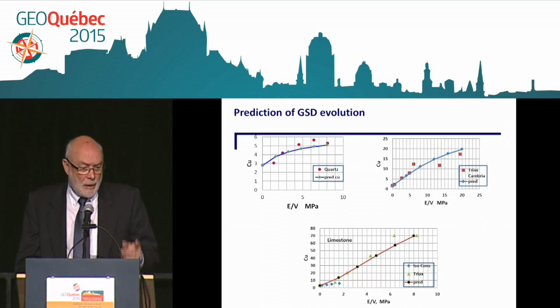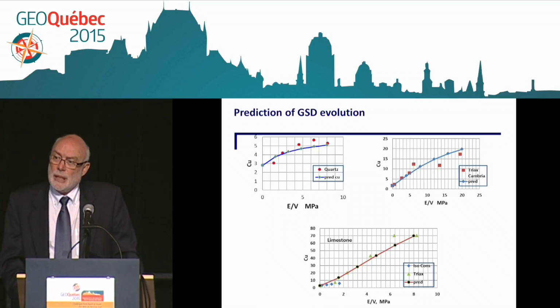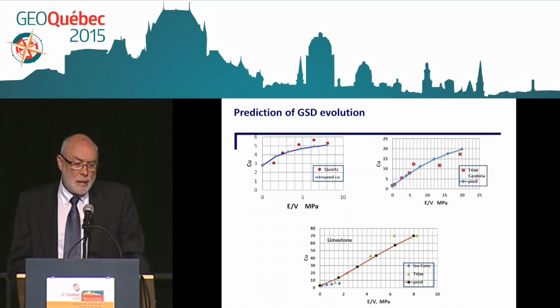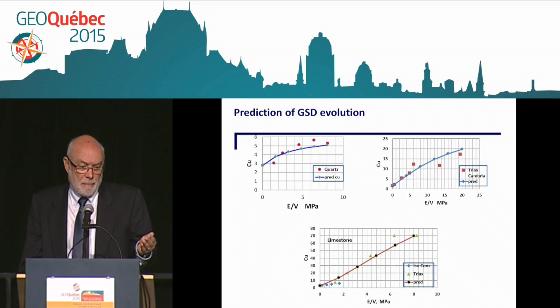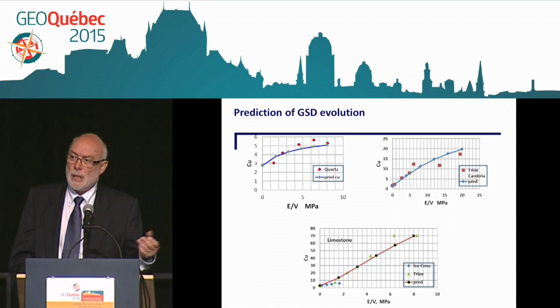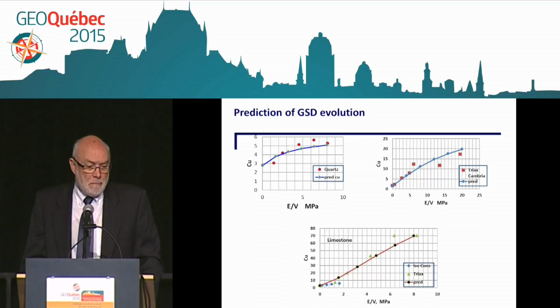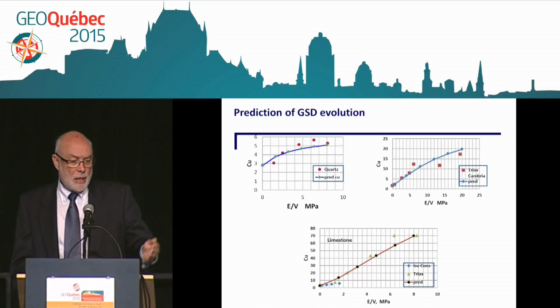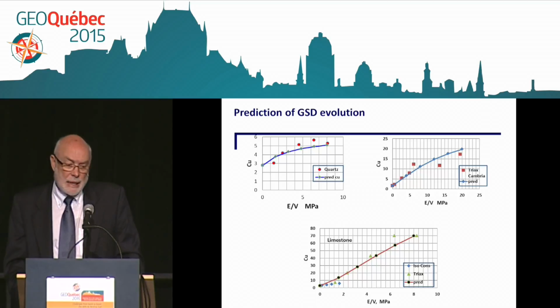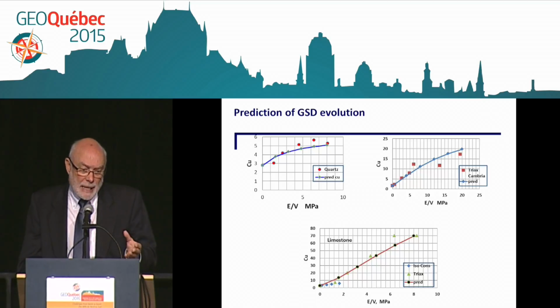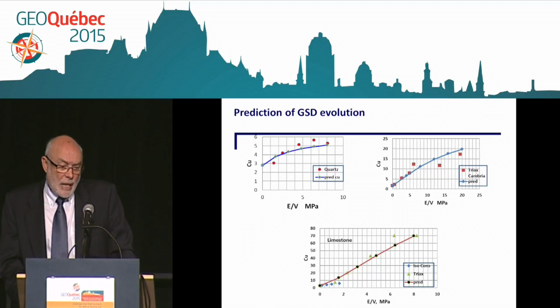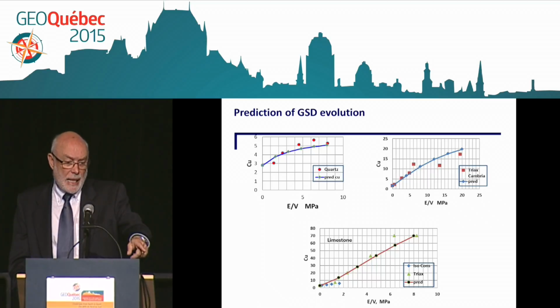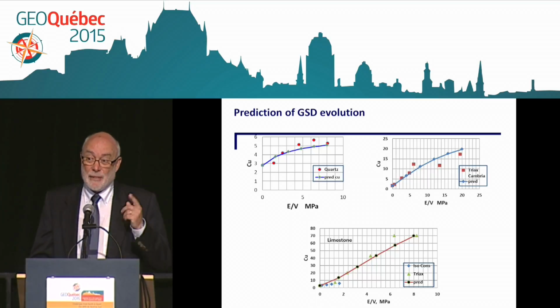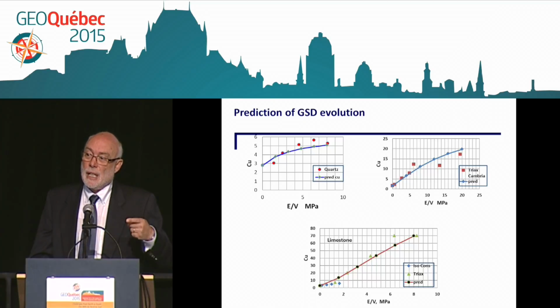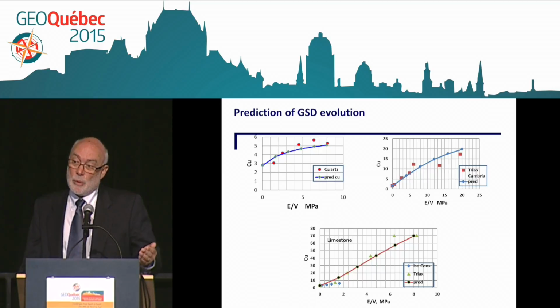It predicts not bad. The first one is for quartz sand. As you said, this is the strongest particle. And you see, we expressed the change in grain size curve by the coefficient of uniformity. It's an easy way to say it. For an initial condition of 3, we only change up to 5 for this sand that is quartzitic. But when we have feldspar sand, we go from 3 to about 20. And in limestone, we have a prediction that is not bad, that goes up to a coefficient of uniformity of 70. That means that I generated a lot of fines during the crushing process. Again, that would be the ultimate.